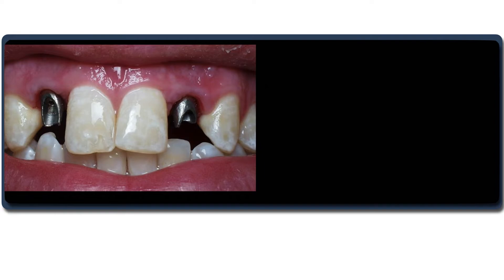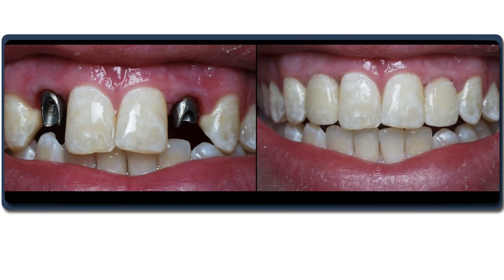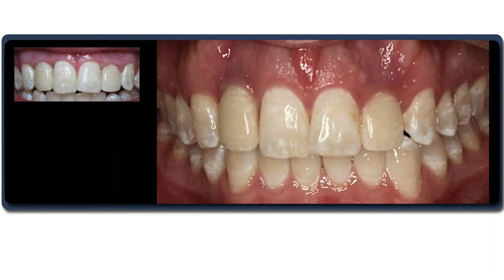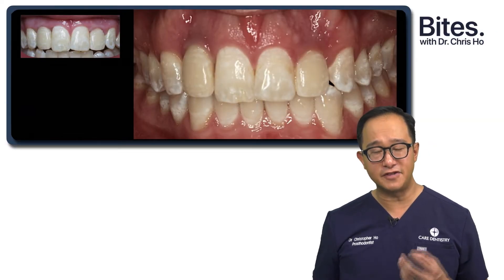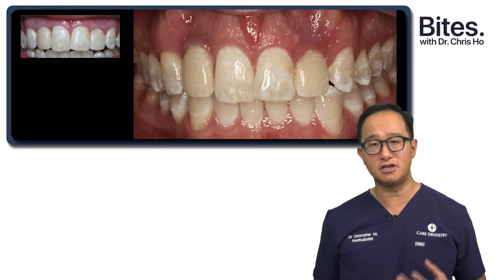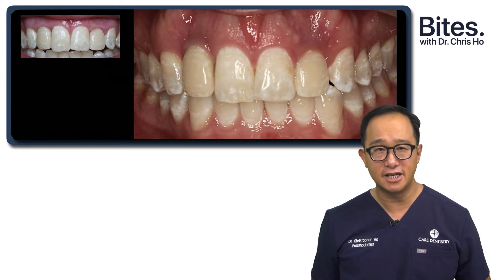If you look at this case with titanium abutments, you'll see there are some PFM restorations that have been placed with a very nice result for the patient. However, 15 years later, we see tissue changes — recession around the lateral incisors — and due to that, we've also seen grey show-through of the titanium abutments through the soft tissue, giving this grey appearance around the tissues.